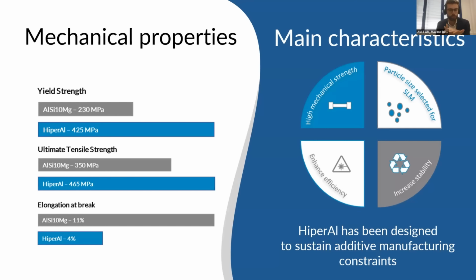And if we look also at the main characteristic, as I mentioned, the high mechanical strength, we eliminate the hot cracking phenomenon by having cooling that is really more homogeneous, with a distribution and dispersion that is completely homogeneous. Our treatment could be applied to really different kinds of particles, different sizes also. We first chose a size suitable for SLM products. In terms of reflectivity, we were able to decrease the laser power by 30%.